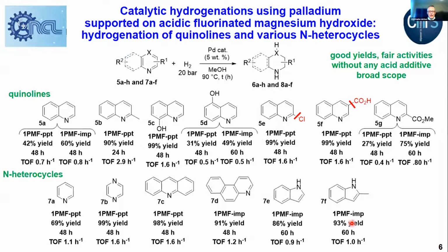Switching to heterocycles, we noticed the hydrogenations required tougher conditions: stronger hydrogen pressure, 20 bar, and a higher reaction temperature, 90 Celsius. Quinolines could be hydrogenated, various derivatives. We noticed, in fact, the impregnated catalyst was more active than the precipitated catalyst for several substrates.